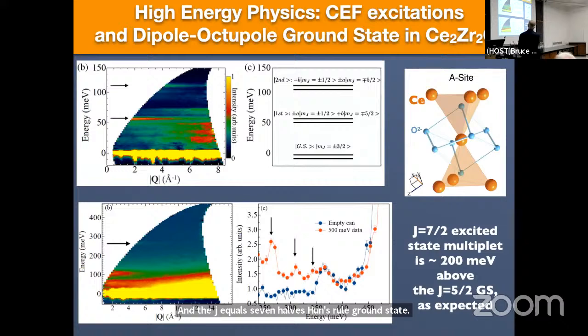Then we can go to a lower energy scale, say 150 meV, okay? And now we're looking at the splitting of the 2J plus 1, 6-fold degenerate Hund's rule ground state. It's going to get split up because the cerium is not in isolation. It's feeling this very electronegative environment from the oxygens. That's the crystal field effect, okay? And that will produce a splitting such that we have a ground state doublet and 2 excited state doublets. And this is an eigenvalue problem.